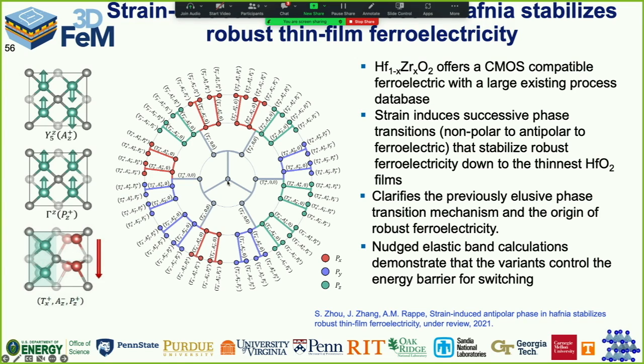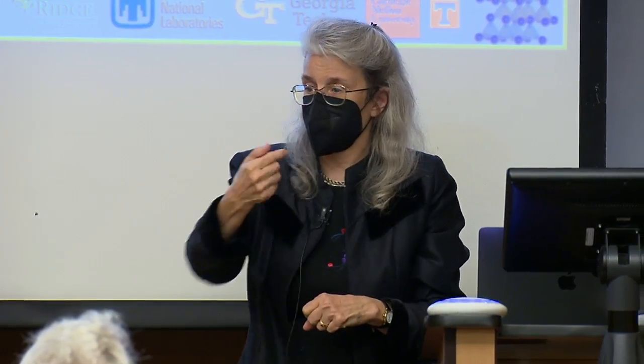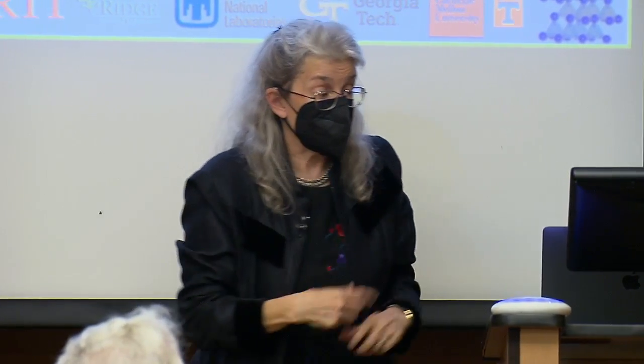So you actually start here with one possible state. That's the cubic prototype fluorite structure. And the first thing that happens is that the material undergoes a tetragonal distortion, which is not ferroelectric. That gives you those 6 states, and it can tetragonally distort this way, or this way. So those are the 6 states, because I can go up, down, forward, back, left, or right. Once I have that tetragonal state, we actually go to an antipolar state, which means on a unit cell level, some of it goes polarization up, next bit goes polarization down, so it's not ferroelectric.